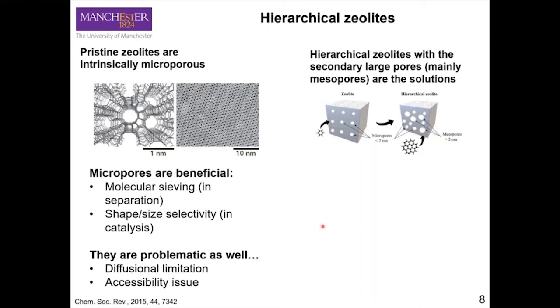we have the concept of developing hierarchical zeolites, which means zeolites with an intrinsic microporous phase that are at the same time also connected with secondary larger pores, mainly mesopores. So we still have the intrinsic microporous zeolite phase to provide the functionality we want from them. But at the same time, we try to dig some highways across the crystal of zeolites and enhance the mass transfer. If any bulky molecules diffuse in, they can diffuse through the large pores, be trimmed smaller, and then later go to the small pores.